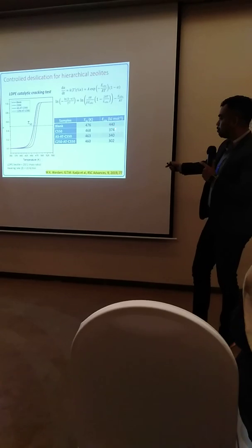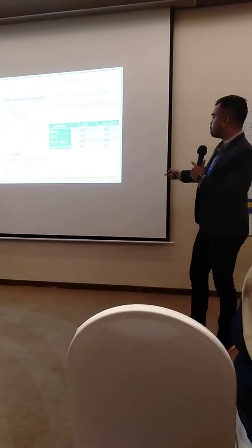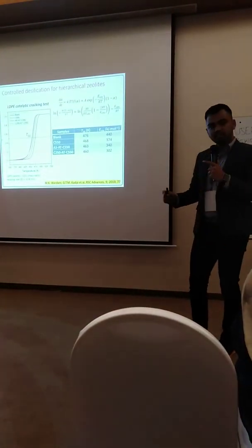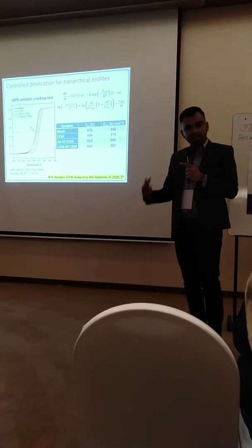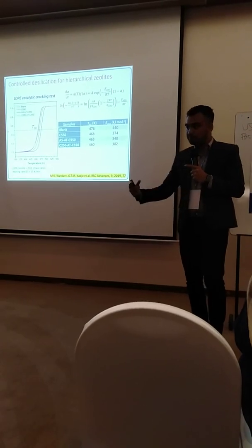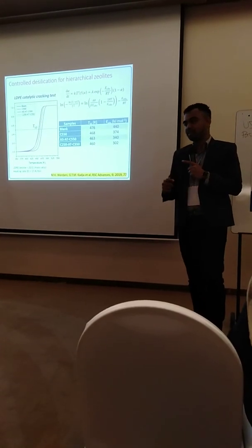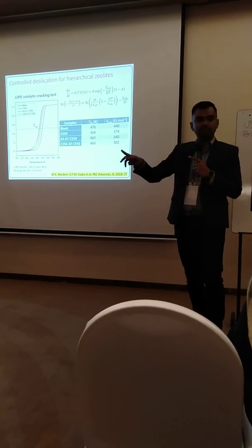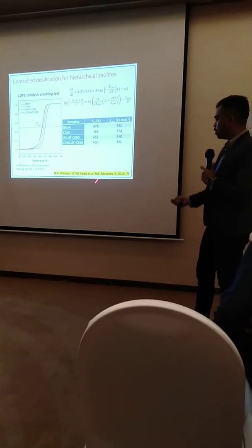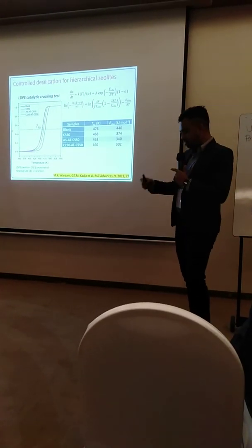But this is purely microporous. When we introduce the mesoporosity, the observed activation energy is further decreased, showing the enhancement of catalytic performance because of the introduction of mesoporosity with the preservation of microporosity. So it's an interplay between microporosity and mesoporosity. This work is conducted by my master students. We have published it in RSC Advances this year.